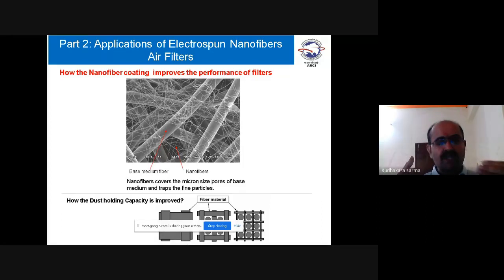One more advantage is we can improve the dust holding capacity of the filtration medium. That means we can hold more dust particles. You can see here in the same area the micron size fibers and the nano size fibers. In the same area, in the left image, we can trap only one particle, whereas by reducing the fiber size, we could trap 9 particles. With that, we are increasing the dust holding capacity. We have two advantages: we are increasing the filtration efficiency, and we are improving the dust holding capacity of the air filtration medium.